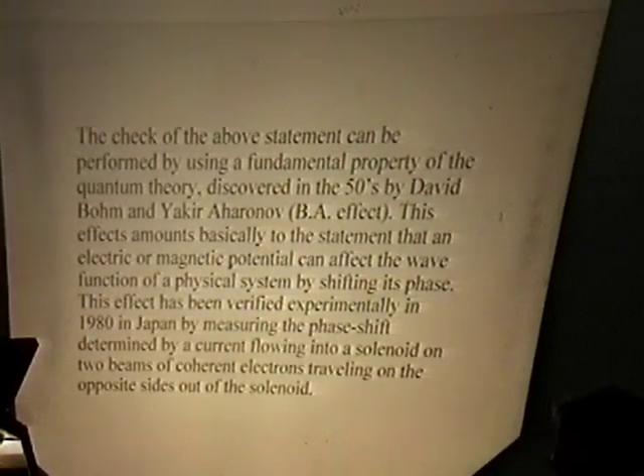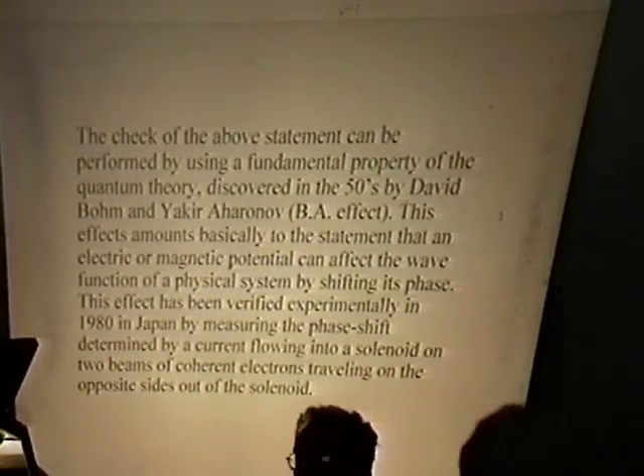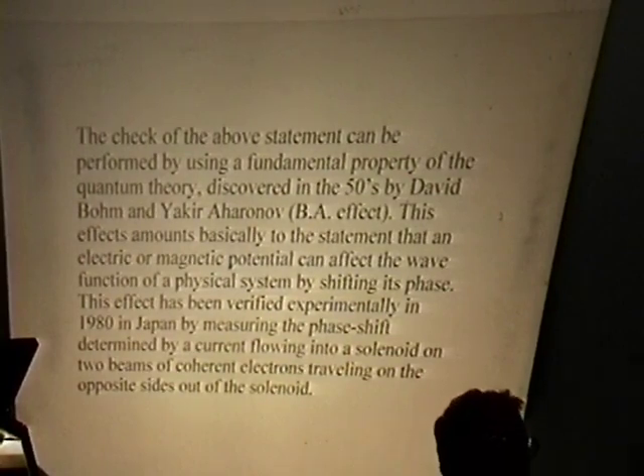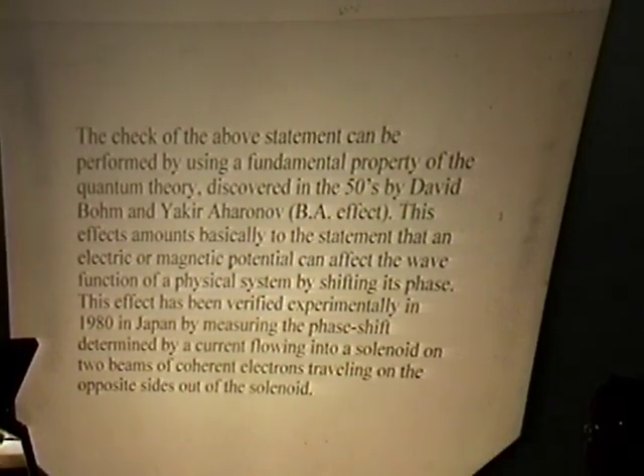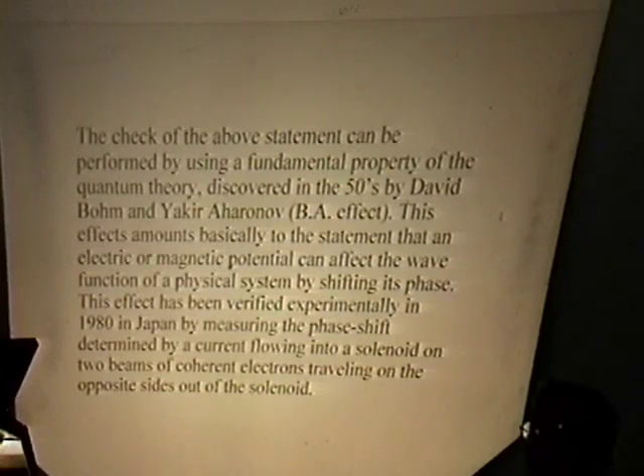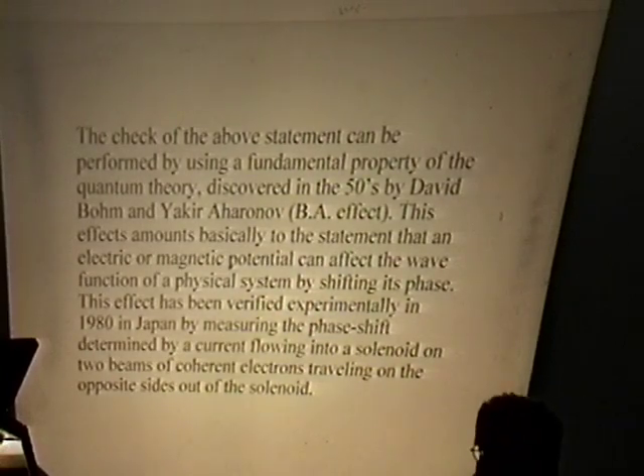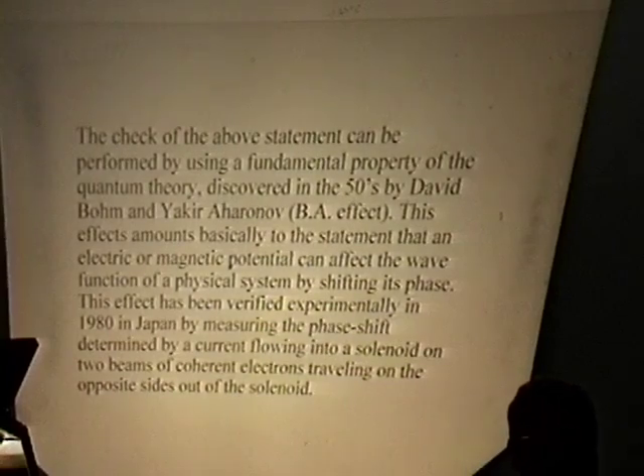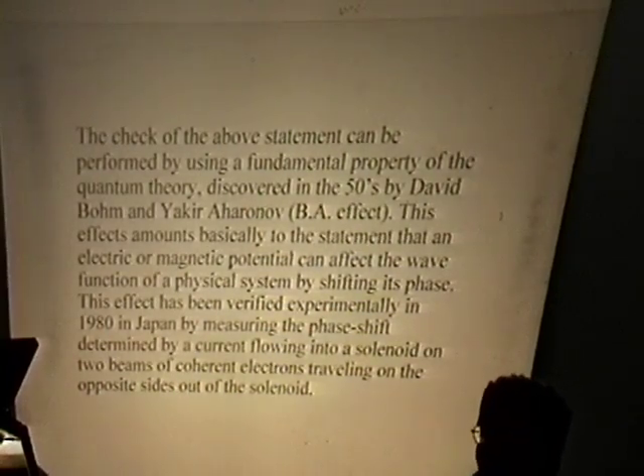And this is a result which doesn't exist, of course, in classical physics, where potentials can be revealed only through their mathematical function, which are the fields. In quantum physics, it's possible to detect the potential directly. Actually, because the potential, through the Schrödinger equation, enters into the phase of the wave function. So by measuring the phase, you measure the potential. And the consequence is that the potential adds up to the chemical potential of the system.